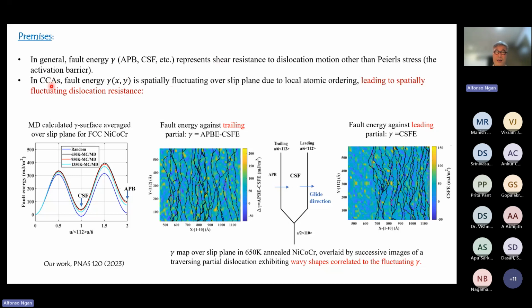However, in a CCA, the fault energy is not constant over the slip plane because we could have short-range order developed, or even without short-range order, down to the single atomic level. If you look at different points over the slip plane, the fault energy would vary. So in general, we would have a profile as represented by this temperature map, where the color scale represents the magnitude of the fault energy. For the trailing case, it will be the APBE minus CSFE. And for the leading partial, it will be just the CSFE alone.